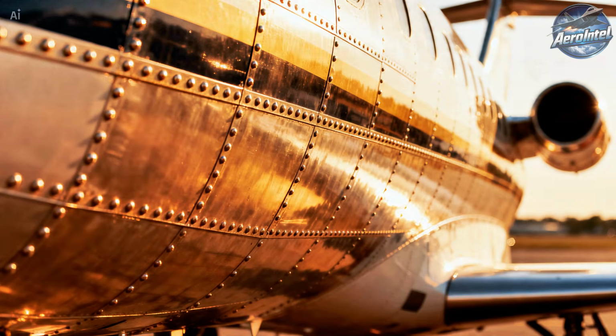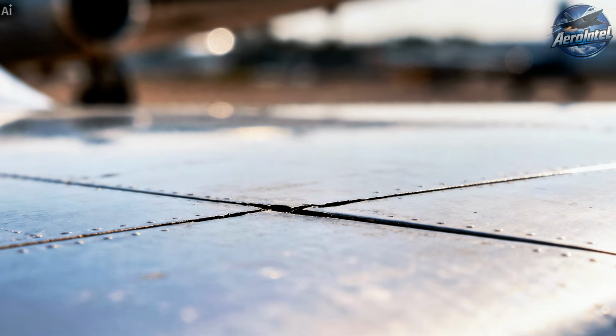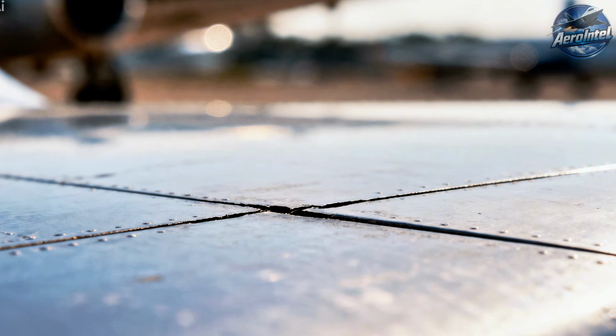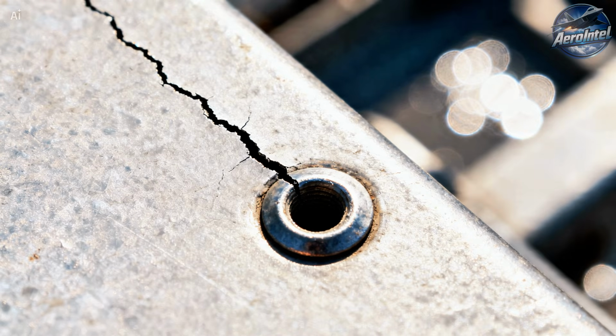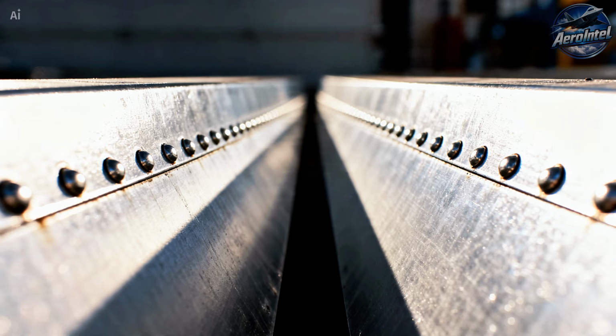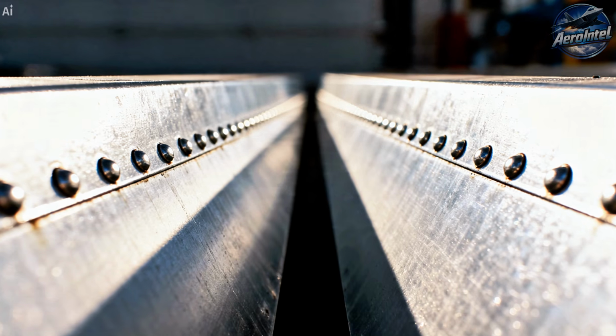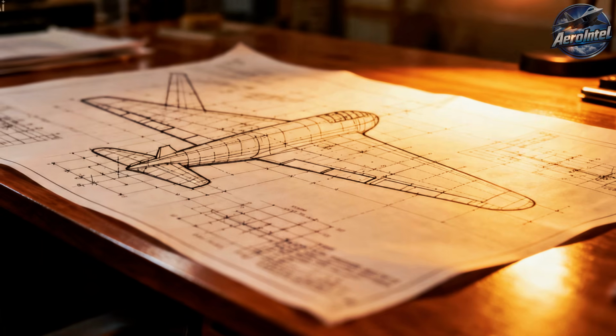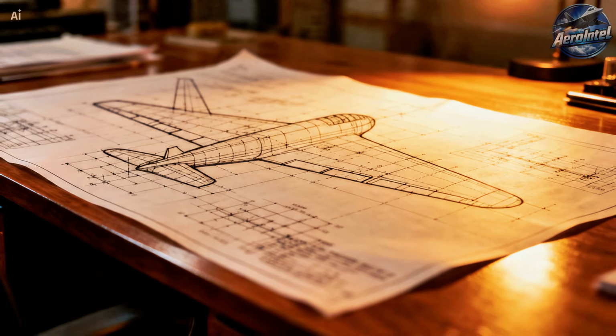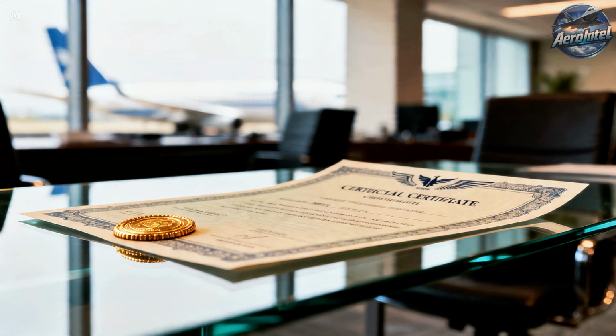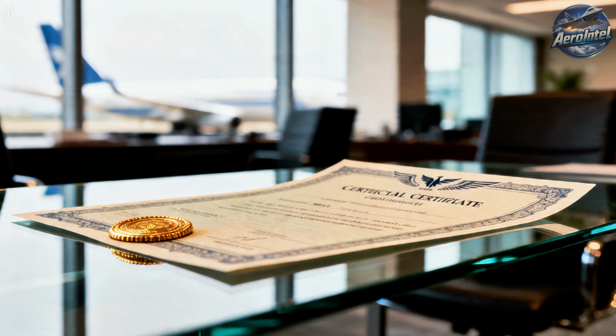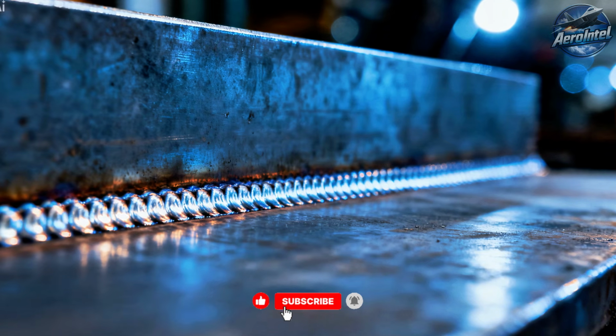A riveted aircraft skin is made of discrete panels, joined at lap joints. If a fatigue crack initiates in one panel, it propagates. But when it reaches the edge of that panel, at the rivet line, it stops. The crack cannot jump the gap between panels. The damage is contained. The structure is fail-safe, which is not just a nice-sounding phrase. It's a specific design philosophy mandated by aviation certification authorities worldwide.